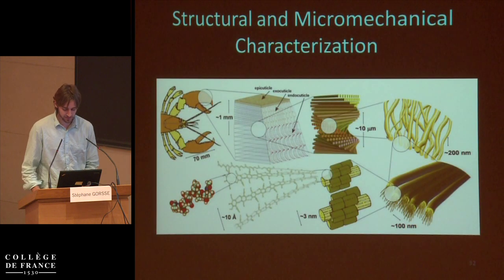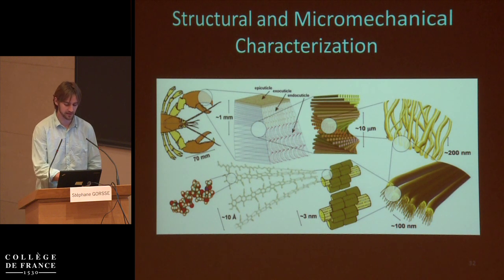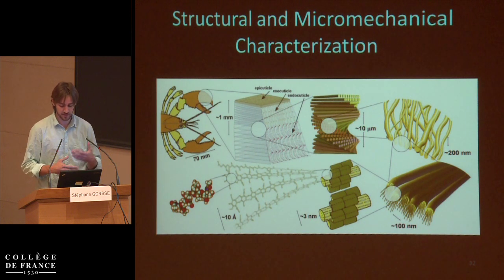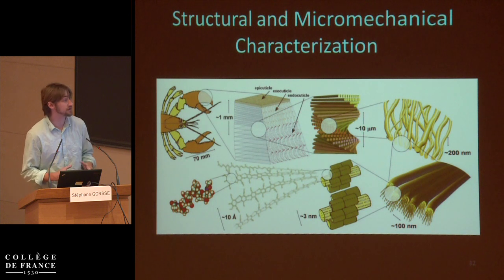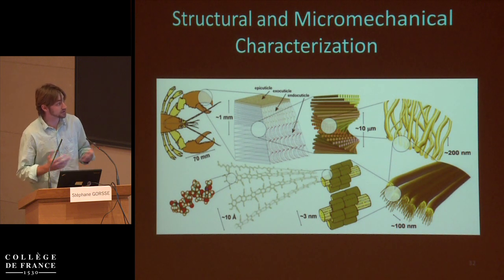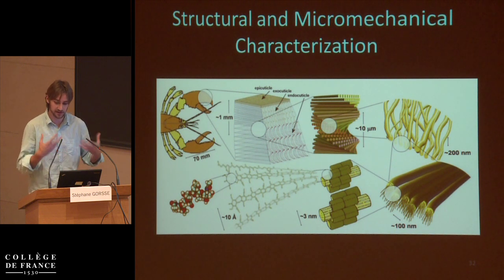But so basically we've just confirmed the structural motif of arthropods, and here we're looking at just the organic. And then if this is a non-crustacean arthropod, then there would be cross links that form in the form of sclerotization. And if it's a crustacean, then you would have mineralization on top of this motif, which is likely, and has been proposed to be a cholesteric liquid crystal that self-assembles and then is rigidified.